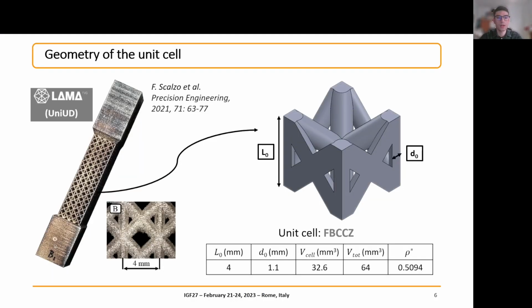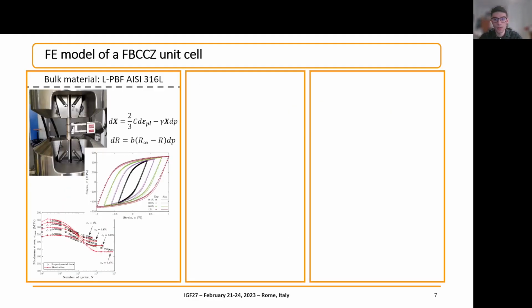The geometry of the unit cell is an FBCCZ with a relative density of 51%. This kind of structure was already manufactured at the University of Udine for another project in the past. And as I said in the introduction, the technology used to manufacture the specimen is laser powder bed fusion, which is an additive manufacturing technique. So regarding the finite element model, the material considered in the simulations is a laser powder bed fusion 316L steel that we tested in low cycle fatigue condition, and then we modeled its cyclic behavior with Chaboche and Voce models.